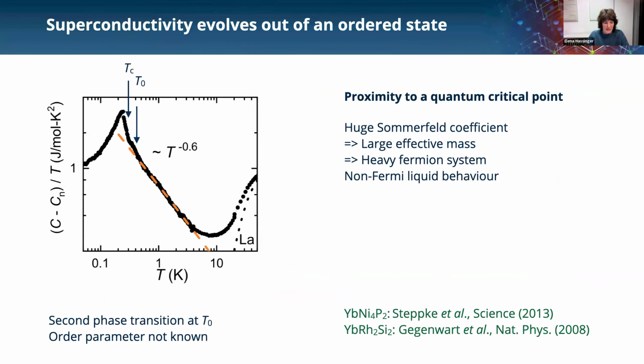Okay, now CeRh2As2, back to our starting material, has another phase transition that occurs above the superconducting state. We call the phase transition temperature T0 because currently we don't know what the order parameter is. In the first samples, it showed up as a small hump above the anomaly to the superconducting state. And this has a very low transition temperature of 0.5 Kelvin also.